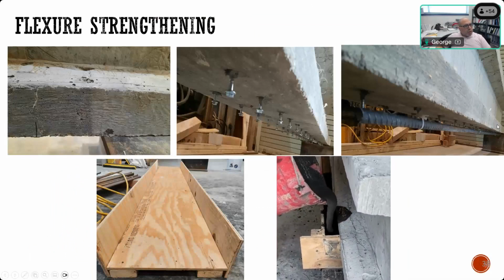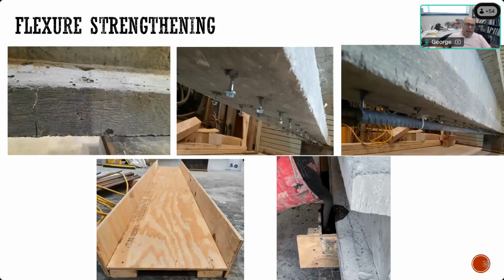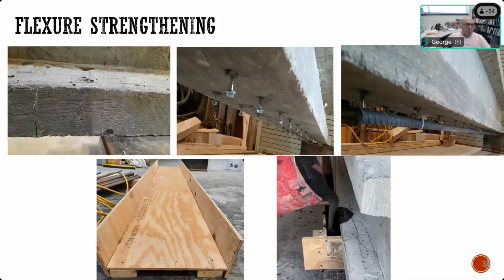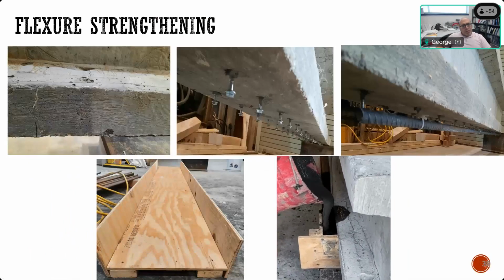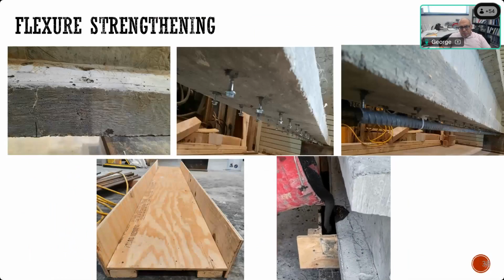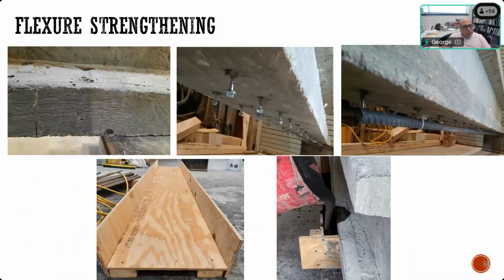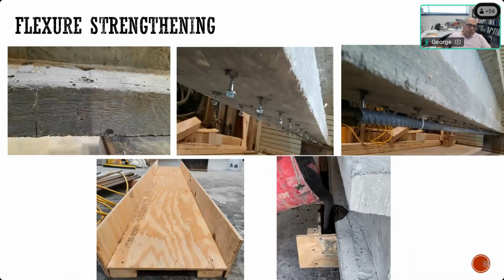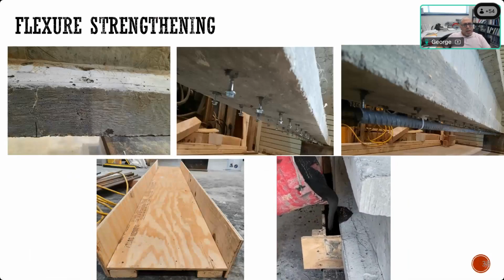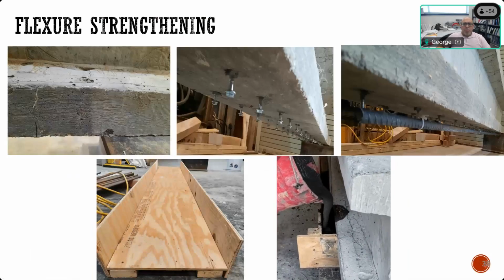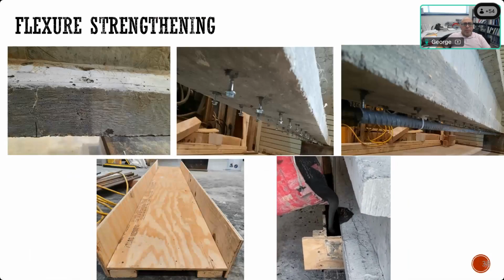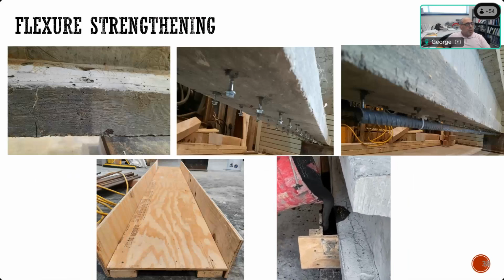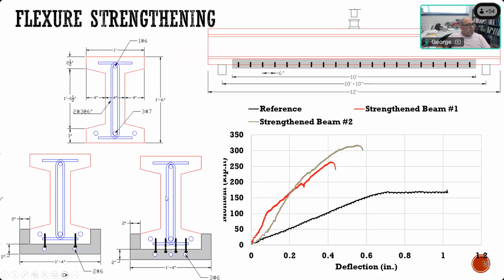Another potential use is to strengthen in flexure by adding UHPC at the bottom of an existing girder in case it needs to be strengthened for lifting the load restriction in a bridge, especially if it is reinforced concrete, not prestressed. You add some anchors as well, add some reinforcement around the anchors, put a kind of a tub at the bottom flange, fill it with UHPC, as you can see, and you can get a cross section that has an additional 2 inches of UHPC with some bars that can also increase the capacity significantly.